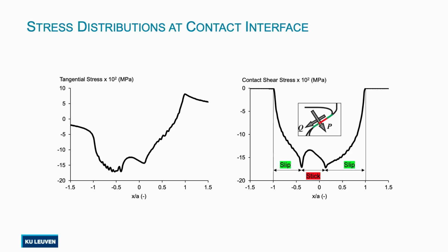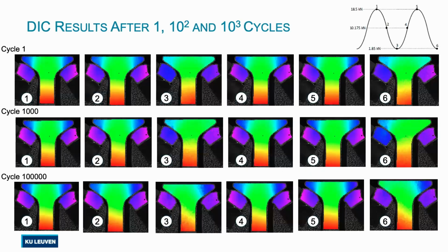Here are some stress distributions, which are very typical for fretting fatigue. Here is the tangential stress distribution at the contact interface, and this is the leading edge of the contact, which is closer to the side where we apply the load, where the stresses are higher. And here, what you see is the frictional shear stress distribution. That's the indication of partial slip conditions. We have sticking in the middle and slipping at two sides. That also confirms that the loading we selected for our test is in line with the more damaging scenario.